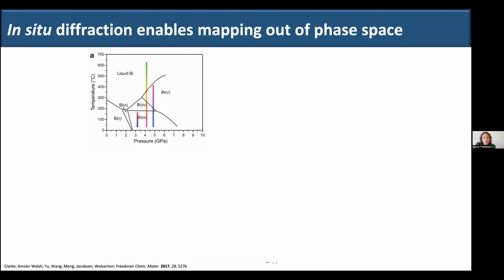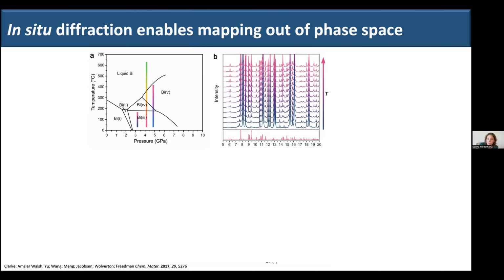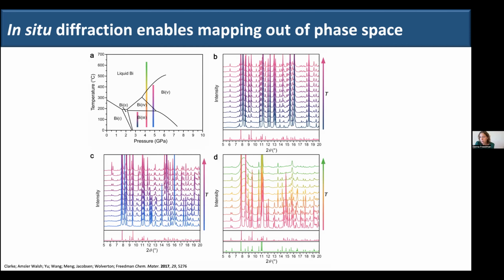But our hypothesis in choosing these specific pressure ranges was that what we wanted to do was progress along the boundaries between the bismuth-bismuth phase transitions and see if those transitions were a fertile point for the synthesis of new materials. Okay, so these are the powder patterns that correspond to those cuts. And for any solid state chemists that are here, isn't this amazing that we can just watch this temperature range and collect the diffraction data and watch how when we pass over structural transitions between the bismuth 3 structure to the bismuth 5 structure, for example, we have the potential for the creation of a new phase. For those of you, if there are any in the audience who aren't used to looking at this, I'll just note that these Roman numerals refer to a different structure type rather than oxidation state.